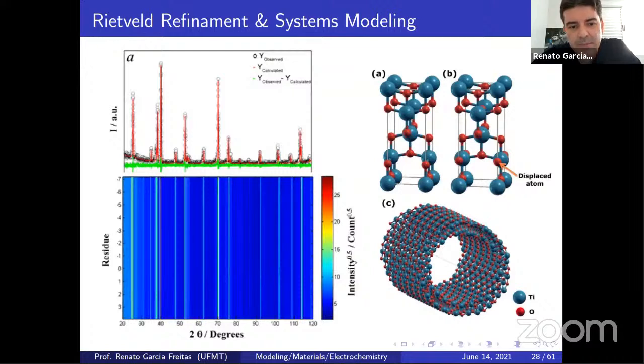And we observed here the diffraction, and we performed the Rietveld refinement. So as soon as we obtain the Rietveld refinement, we obtain the CIF file, the crystallographic information file. So it's possible to convert that electrode into the unit cell, isn't it? So we have the anatase titanium oxide like this one, and we push this oxygen here to induce a defect, as discussed, the band gap is a function of defect. Professor Elson Longo used to have several models for this one as well.